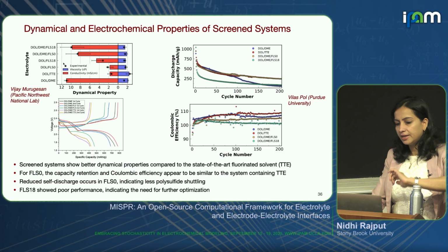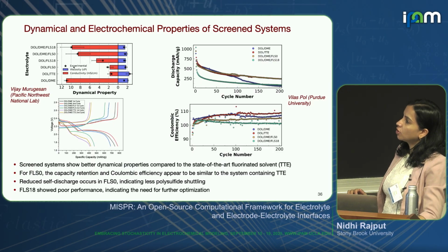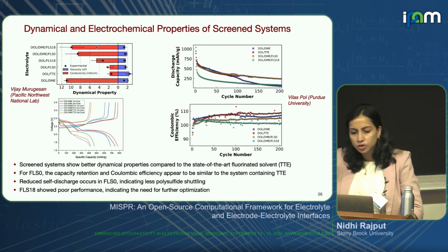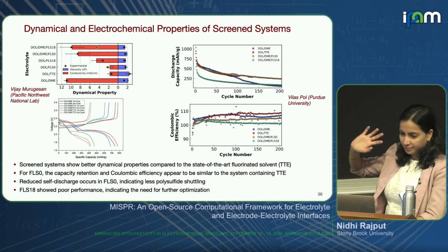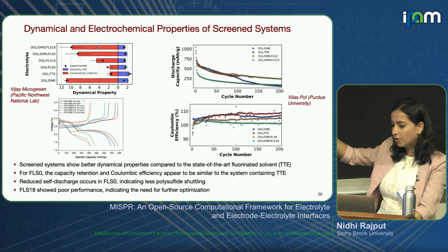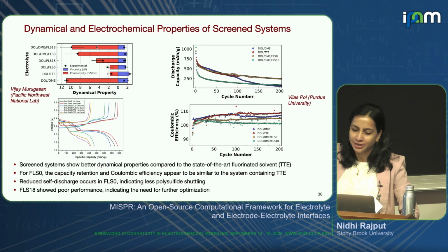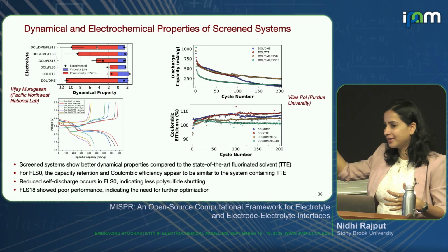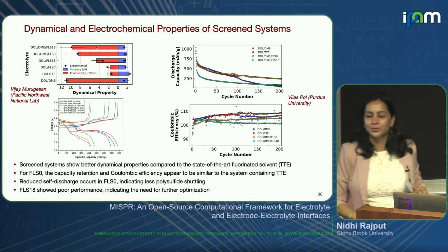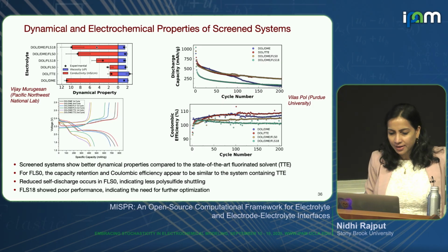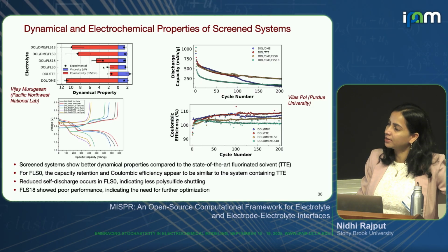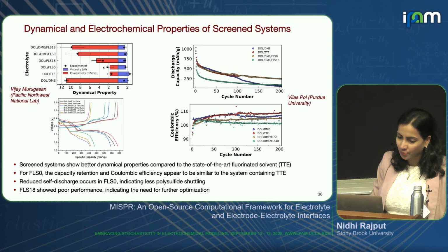So here you're looking at the experimental viscosity and ionic conductivity results in comparison with what we got from simulations. First of all, with this very vanilla flavor of all-atom force field MD simulations, the predictions look great to me, because I have seen 50% error bars in viscosity calculations when we do all-atom MD simulations. So overall, for newly proposed electrolytes, these results seem acceptable to me.